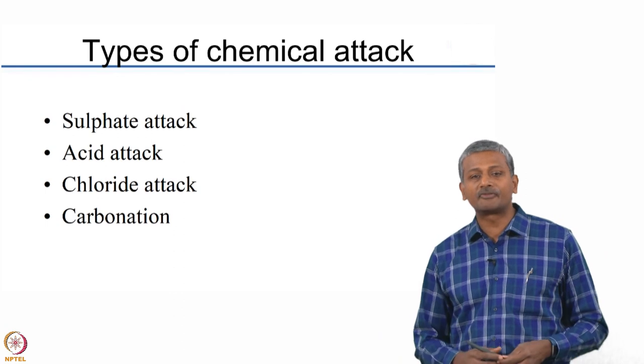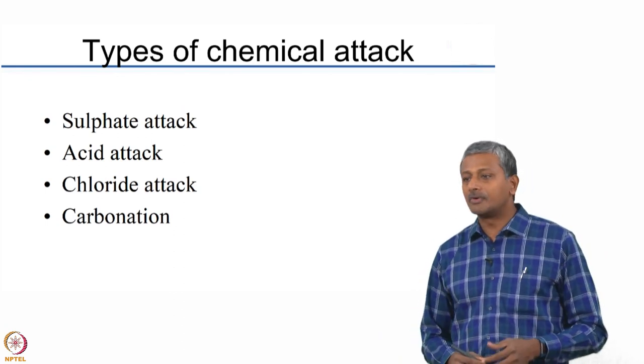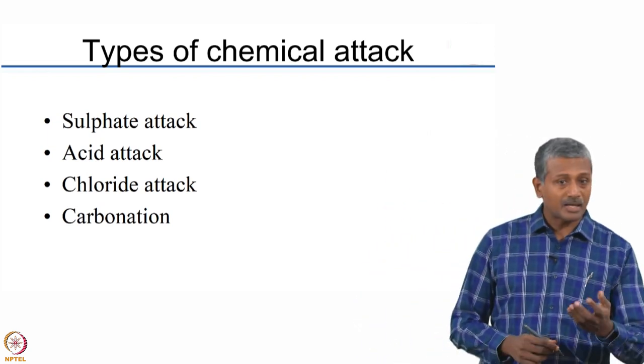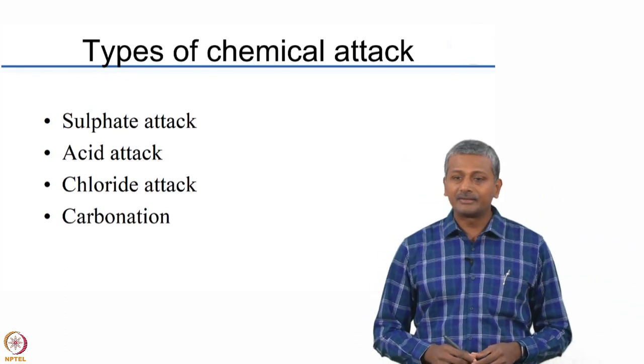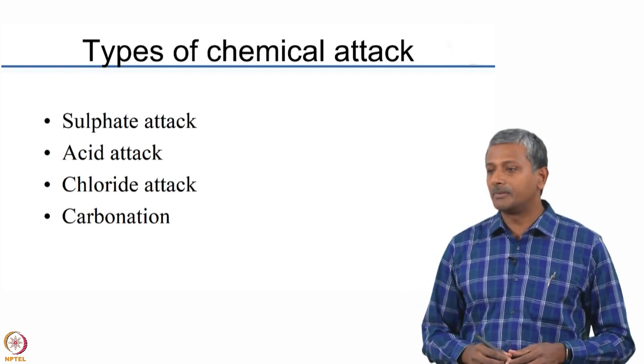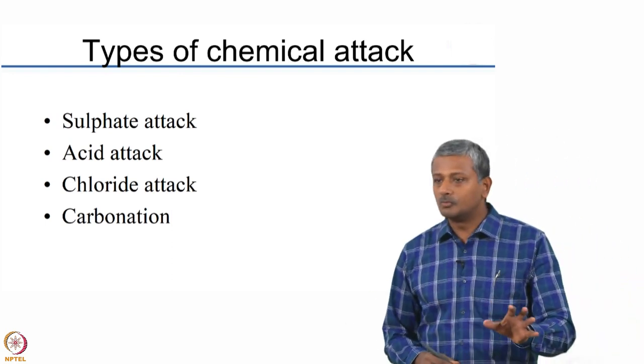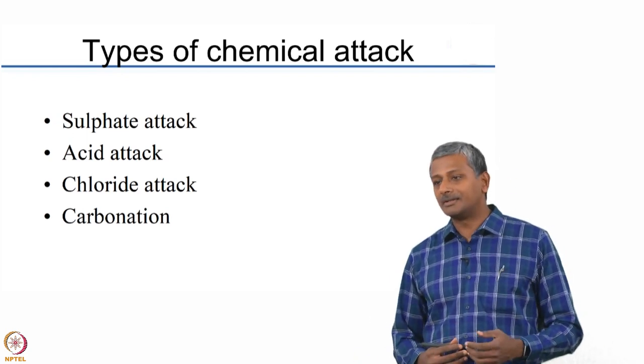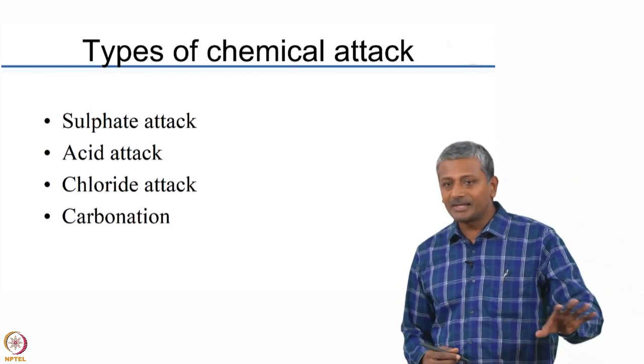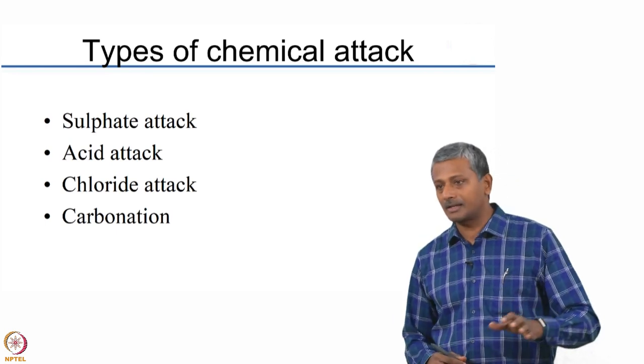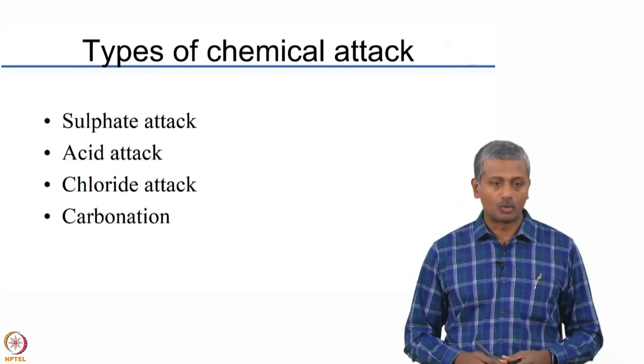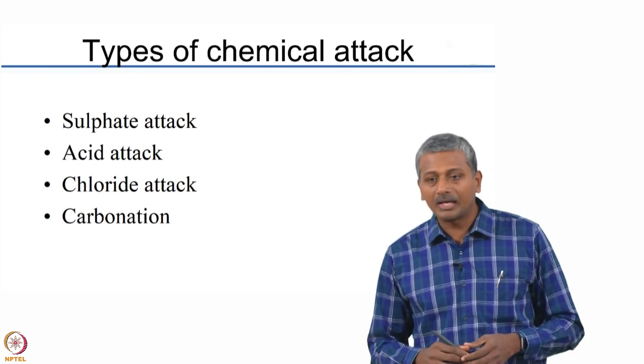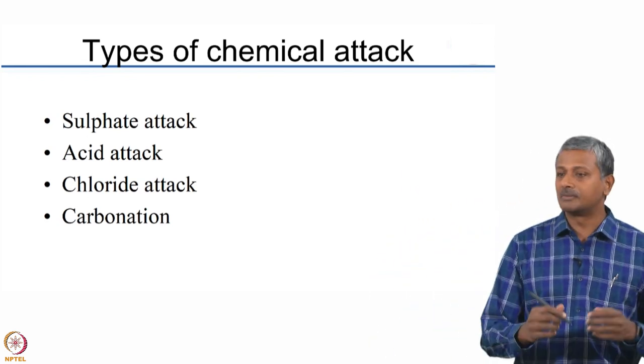There are generally several other types of chemical attack apart from sulphate attack. For example, you may have acids attacking concrete, or chlorides directly attacking concrete as in the case of sea water and sometimes ground water. There is also carbonation — attack of concrete by atmospheric carbon dioxide. These chemical attacks have different mechanisms and reactions, but one thing they all have in common is the requirement for water, because chemicals in the external environment need a liquid or aqueous medium to be carried into the concrete.